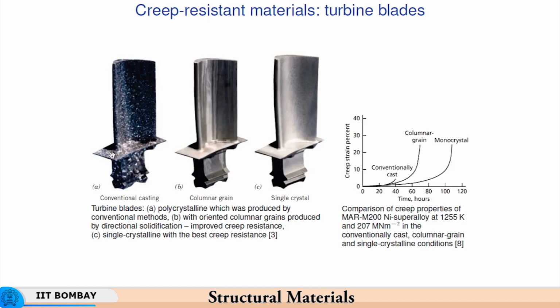So, this will not be high temperature resistant, whereas here the high temperature resistance, that is creep resistance, will be significantly higher, because the grain boundary area is much smaller than here, and even if the grains are larger, there is also directionality. The directional solidification has imparted directional properties to the turbine blade, and therefore we will have greater strength in the direction of applied loading.